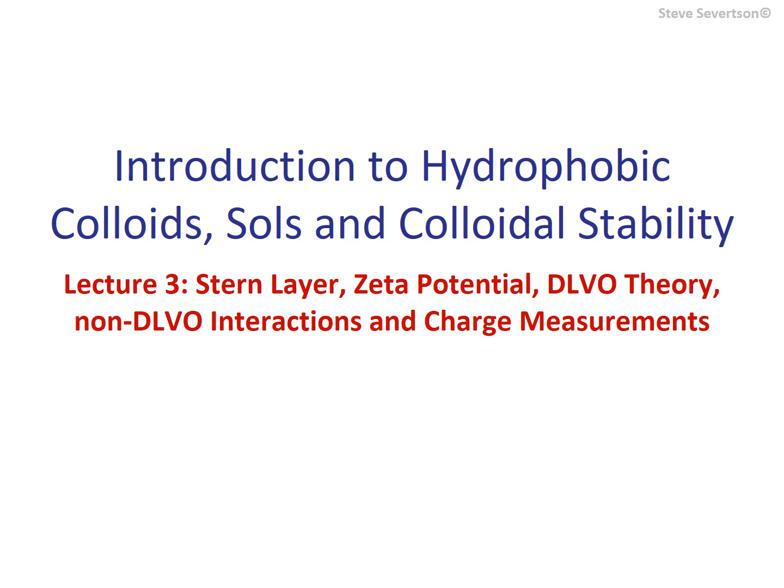We begin this chapter by removing one of these assumptions, specifically the treatment of ions as point charges. By considering the size of an ion and its hydration shell, we limit how close such species can approach the surface, which introduces a new region to the electric double layer, a region located directly adjacent to the surface where there exists a separation of charge. This is known as the Stern layer. Rather than complicating matters, consideration of the Stern layer helps justify the general applicability of our previous results and ties the model to experimental measurements of zeta potential.